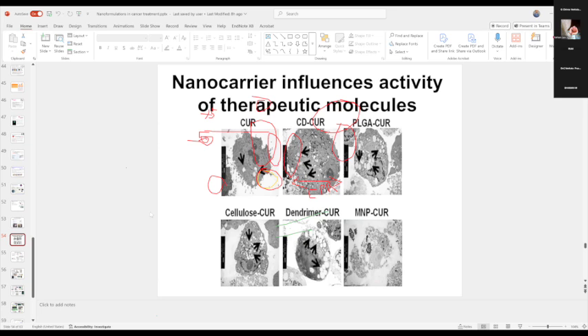Then we identified that, you see the structure in the curcumin alone, it shows very few vacuoles formed in the cell structure because of curcumin. Okay, when you see cyclodextrin curcumin treated cells, there are a little bit more vacuoles formed. PLGA curcumin based, you see even more. Cellulose curcumin nanocrystal, you will see a greater number, and dendrimer curcumin also, a greater number of vacuoles, but all of them are better than your free molecule. Okay, where the free molecule induced only 4 vacuoles, all the others produce more than 20 vacuoles. That means this drug is more potent when you encapsulate it in various types of nanomaterial.